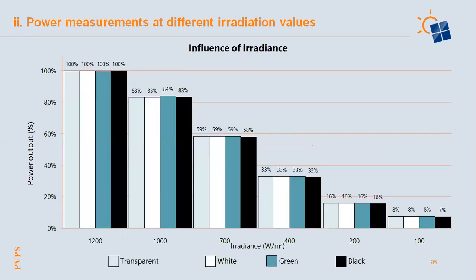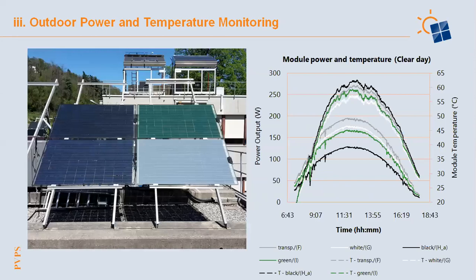And this can be seen also here in the outdoor monitoring of these modules, because as you can see here, the power output of the black modules is the lowest one, due to the fact that the light is absorbed, and this absorption is also converted into heat, and this increases the operating temperature of the modules, and the power is negatively affected. Whereas, for instance, for the white model, the operating temperature is lower because the radiation is reflected, even if we still have quite good power output.